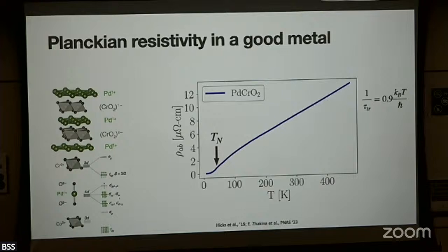Yeah, resistivities are either much smaller than or much bigger than h over e squared, which is 25 kilo ohms. Equivalently, k_F l, where k_F is the Fermi momentum and l is the mean free path, is much smaller than or much bigger than 1. Oh, that's this analysis I told you before. So here you measure the DC resistivity, fit it to a Drude-like form. You know n, you know m star from some other measurements. You fit it. Yeah, it has all its assumptions, approximations. And maybe the interesting question is to ask, in spite of all this, why does it always turn out to be an order 1 coefficient?